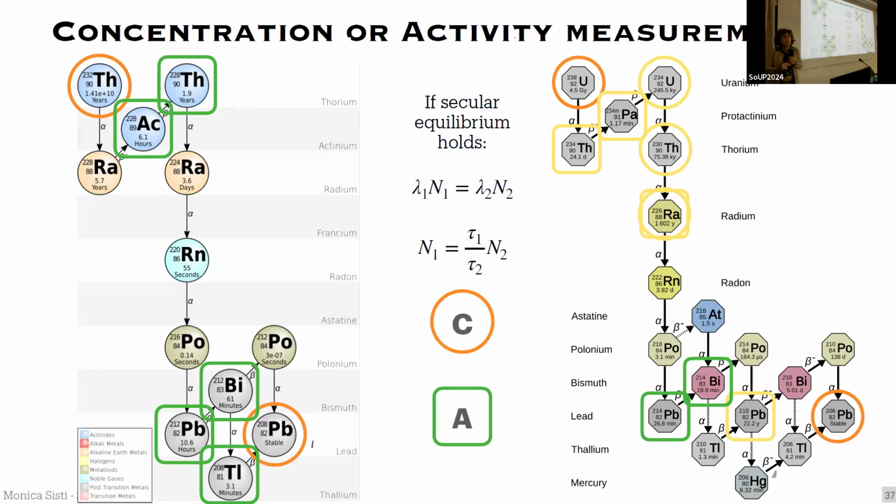But with good germanium detectors, you can detect these lines, if they are present, of course. Yeah, similar for lead-210, right? Similar for lead-210, yes, sorry, I didn't mention it, because lead-210 has the gamma line at 46 keV, which is very low. So this is also very difficult to detect, and that's why it's difficult to assess the lead-210 content of the material.